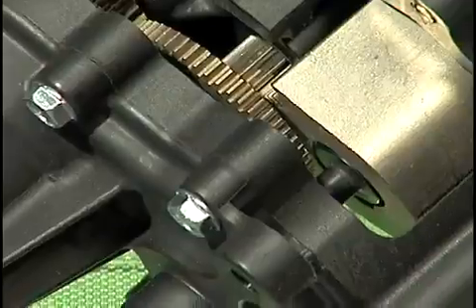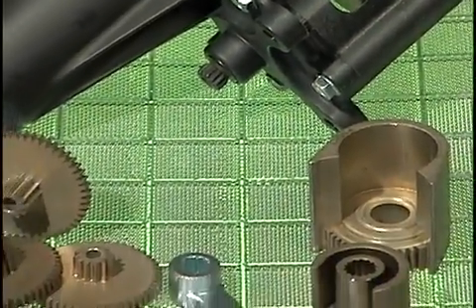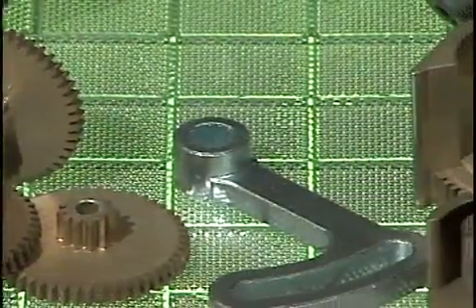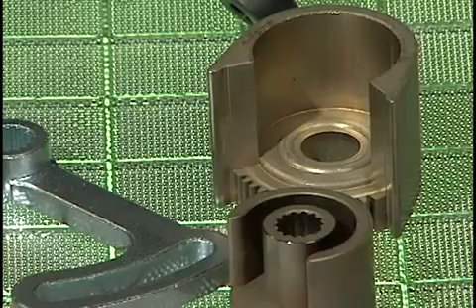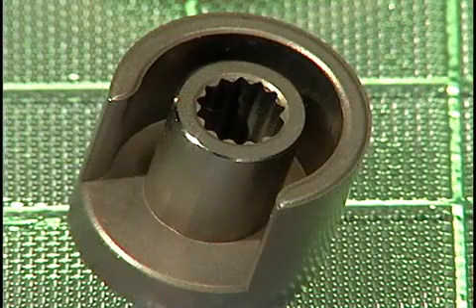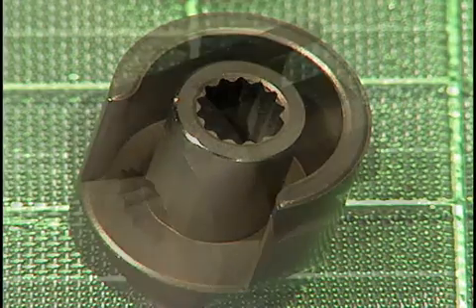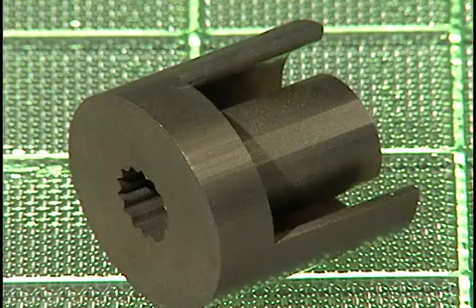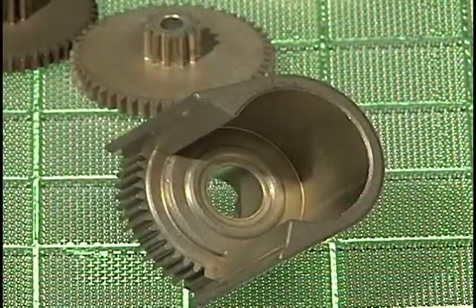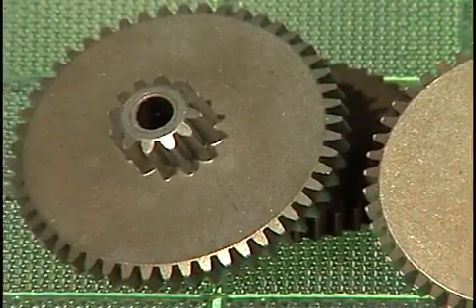By changing the electrical switch, the assembly actuates the transmission linkage to engage either forward or reverse gearing. The parts are made to a typical density range of 6.6 to 6.8 grams per cubic centimeter. Most of the parts require heat-treated properties of 120,000 psi tensile strength, 110,000 psi minimum yield strength, 43,000 psi fatigue strength, and a typical hardness of 35 HRC.